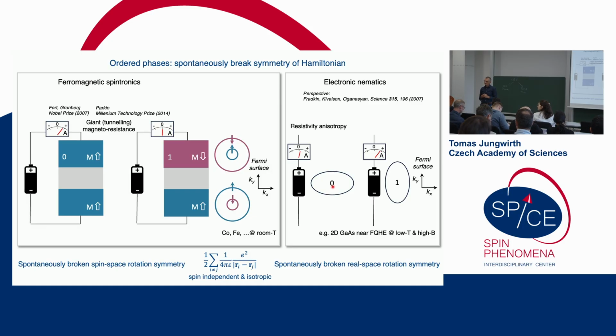So there is a question whether it's orbital ordering or it has magnetic ordering, or it is what you call Pomeranchuk. Pomeranchuk, by the way, is a strong coupling interaction phase transition, and I don't know if there is a single example that justifies the use of Pomeranchuk. It's a nice tool for us theorists, but we need to distinguish the symmetries of the phase from the microscopic mechanisms behind the phase. Then people discuss, because they don't make this distinction, they say, no, it's orbital ordering or it's spin ordering, and that's irrelevant. Okay, what matters is what symmetry the state brings.